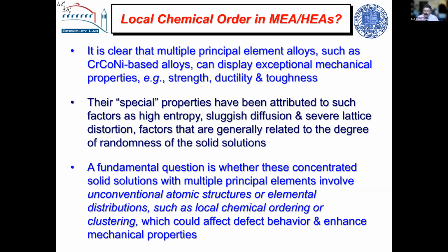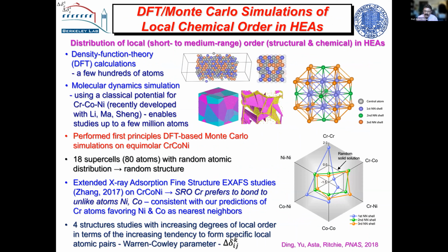So the first thing we did is we did work on DFT, or density functional theory. There was some evidence from Oak Ridge on EXAFS, X-ray absorption fine structure, which suggested that in these multiple principal elements, certain bonding was preferential. For example, the chromium atoms tended to prefer to bond to unlike atoms rather than like atoms. This is known as the Warren-Cowley parameter, and chromium-chromium pairs are disfavored, but chromium-nickel and cobalt-nickel are favored in terms of preferred groupings of atoms. So we basically used Monte Carlo simulations based on DFT. Not too many atoms, unfortunately, because it takes too long.